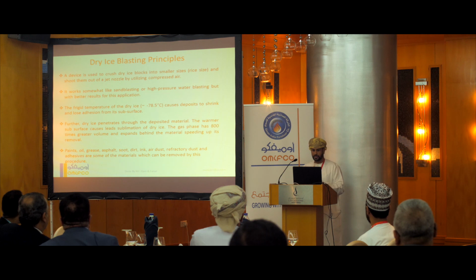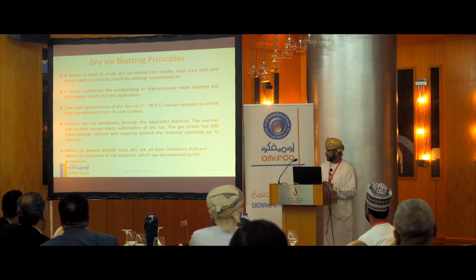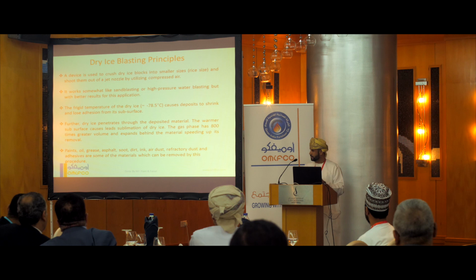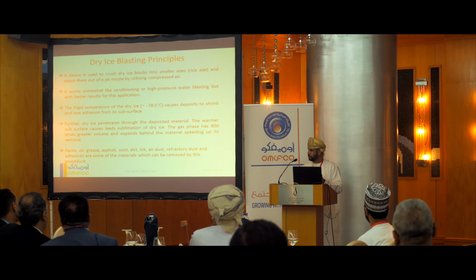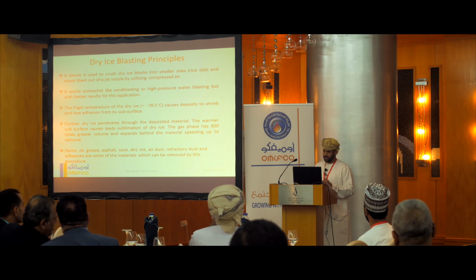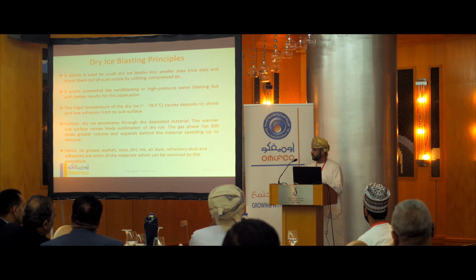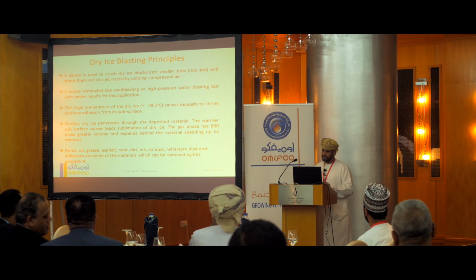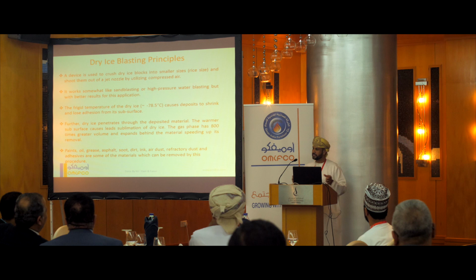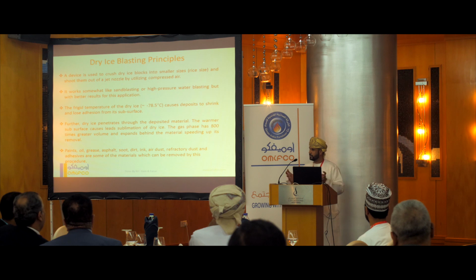This dry ice penetrates through the deposit material. The warmer surface causes sublimation of the dry ice. Sublimation is a phenomenon where it changes from solid to gas directly without any liquid phase. The gas phase has 800 times greater volume and expands behind the material to lift it off and remove any dust. It can remove paint, oil, grease, asphalt, soot, and refractory dust. The main deposit on those coils is refractory dust, and also dust from the air coming out from the burners.